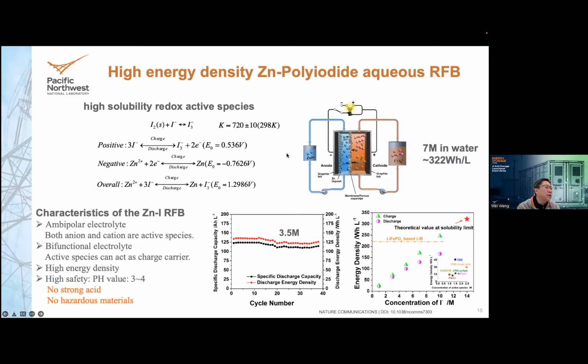So based on that, we developed a zinc iodide flow battery. This flow battery has some very interesting characteristics. It has what I call an ambipolar electrolyte. Basically, both the anion and the cation are active energy bearing species. Normally, for example in the vanadium flow battery, the anion, the sulfate ion, is not active. It's just a compensating ion. But in this design, both ions are active, and it has a bifunctional electrolyte. The zinc ion functions as both the charge carrier and the energy bearing ion. So this chemistry was able to reach a very high energy density.